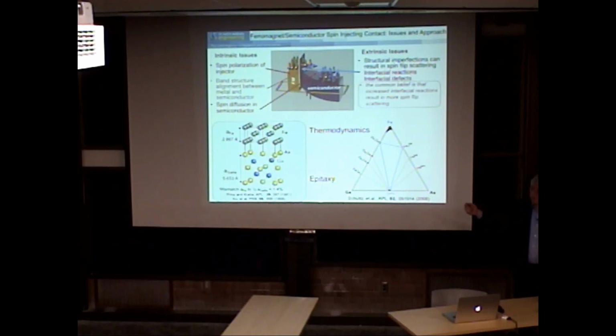If it's one atomic layer of iron arsenic, that is an antiferromagnet. So is that good or bad? First thing you say it's bad. If I get more and iron starts diffusing into the gallium arsenide, and what I'm going to point out here, if I show you the ternary phase diagram that we believe is the correct one, for something to be stable, there must be a tie line, say from iron to gallium arsenide, and there's no tie line, which says it's not thermodynamically stable. That says that if I put iron down, I expect it to react. And in fact, what I expect to get is Fe3Ga and Fe2As. So that tells me immediately that thermodynamically, this is not a stable interface.